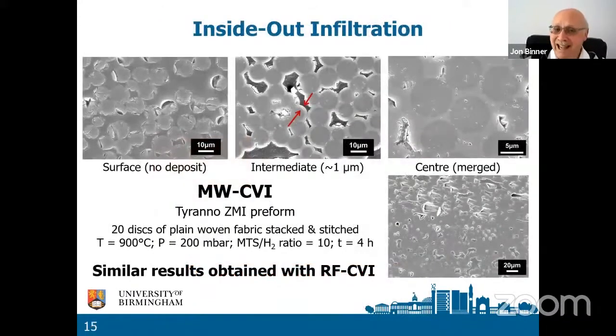And we can see this here. So this is actually for a SiC composite, a silicon carbide composite. And what we've done, you can see the conditions there: it's 20 discs of fabric stacked and stitched together. The temperature is 900 and the pressure is 200 millibars and so forth. The time is just 4 hours.